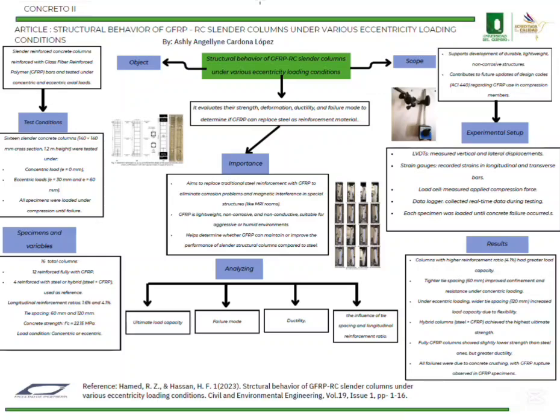Now let's discuss the main results obtained from this experimental program. First, as expected, columns under eccentric load showed lower load capacity than those under concentric load. This happened because eccentric loads produce bending moments that reduce the effective compressive strength of the section. Regarding the type of reinforcement, the hybrid columns achieved the highest load capacity, followed by steel-only columns, then the GFRP-only columns, which still performed close to steel but with a slightly lower strength.